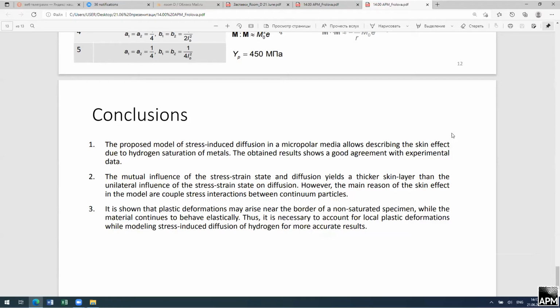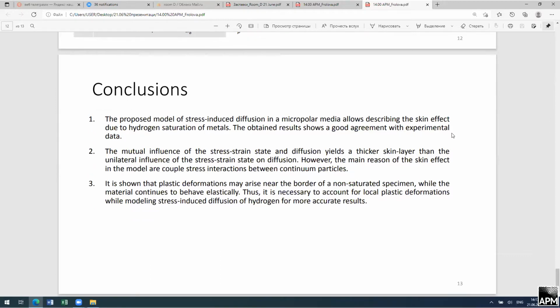So our proposed model of stress-induced diffusion in micropolar media allows us to describe the experimentally observed skin effect. And here we discussed three skin effects. First is the non-uniform distribution of stresses and strains due to couple interactions between particles. Second skin effect is the non-uniform distribution of hydrogen. And the third skin effect is about probable plastic deformation in the vicinity of the border. So thanks for your attention. Any questions?